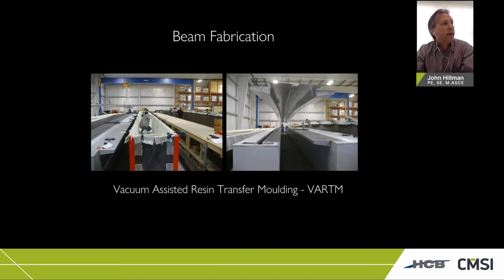Here you can see the manufacturing process. They just throw everything in a closed mold, lay in the glass, the steel, the foam. The foam core comprises the interior volume that doesn't contain the arch. Pull vacuum on it, infuse the resin in, takes about half an hour. You can build a beam a day in each mold. Then you see on the right there, just setting the composite lid on top of it to get the final, not the roadway surface, but basically a stay-in-place deck form.